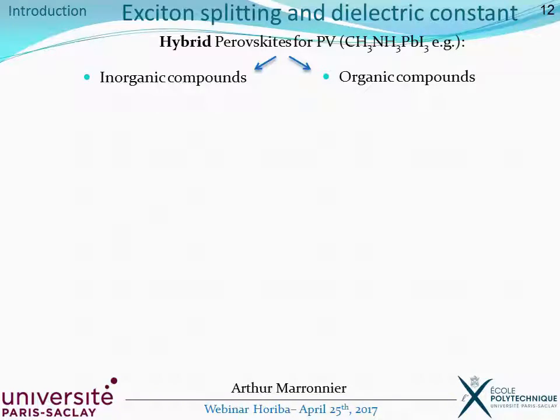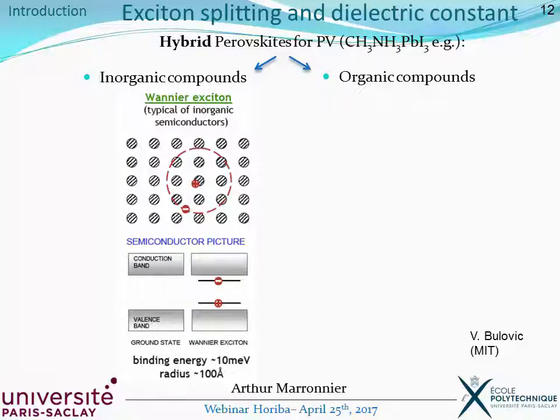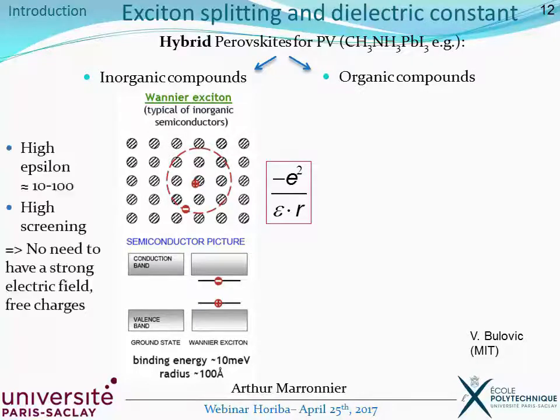Now, why are we interested in the dielectric properties of these hybrid perovskites? Well, as far as the dielectric properties are concerned, inorganic and organic compounds behave quite differently. On the one hand, inorganic compounds have Wannier excitons, which means very delocalized excitons with a low binding energy. And when you look at the formula for the binding energy, it is associated with a high value for epsilon, the dielectric constant, usually between 10 and 100.